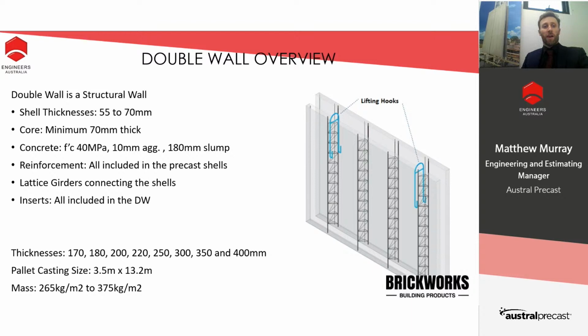All the reinforcement that you would have in the in-situ wall is included in the precast shells of the double wall. The lattice girders that you can see here connect the two shells together, and they serve two functions. The first function is to connect the two shells together in the temporary state. So the embedment of the vertical bars of the lattice girder requires at least a minimum of 15 millimeters to connect the two shells together. But the second function is to make the wall act as a composite structure. The reinforcement that crosses the interface from the lattice girder contributes significantly to this.